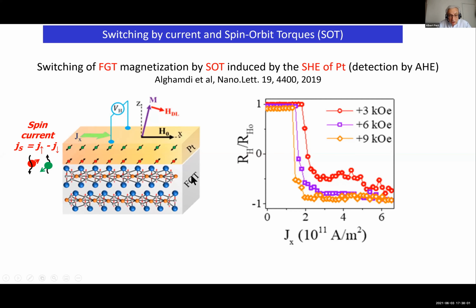And this is an example of FGT with a spin Hall effect induced by the current in platinum. So the current is going this way, the spin current is vertical, and as a function of the current, you can see the switching from one orientation of FGT upward to downward, detected by the anomalous Hall effect. Of course, what is known also for the 3D materials is that the switching by the spin Hall effect, by the spin orbit torque, is possible only if you also apply a field to break the symmetry.